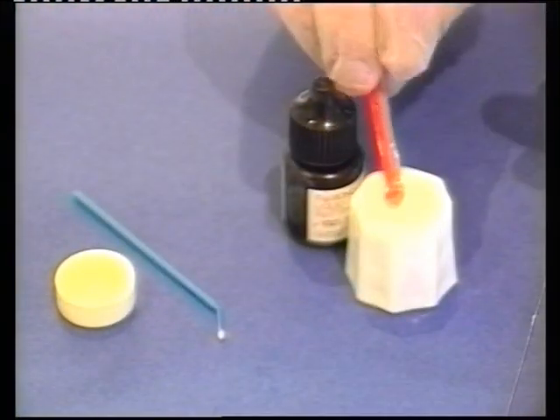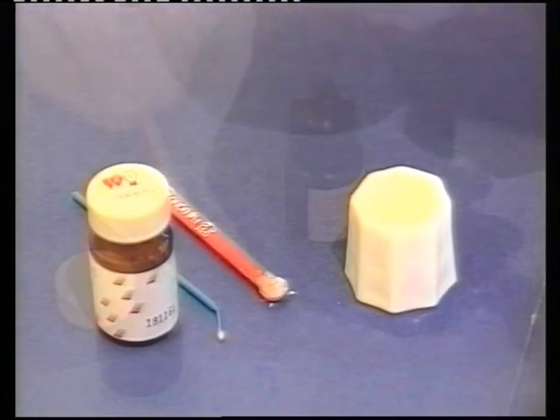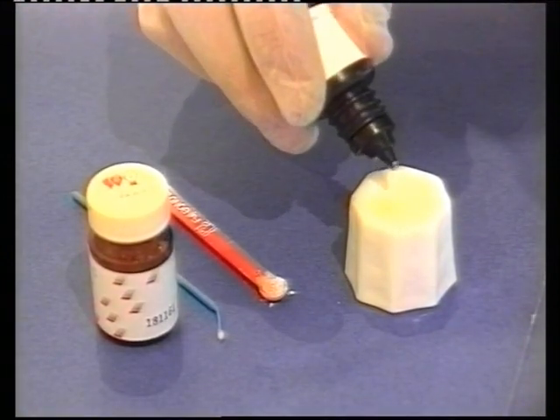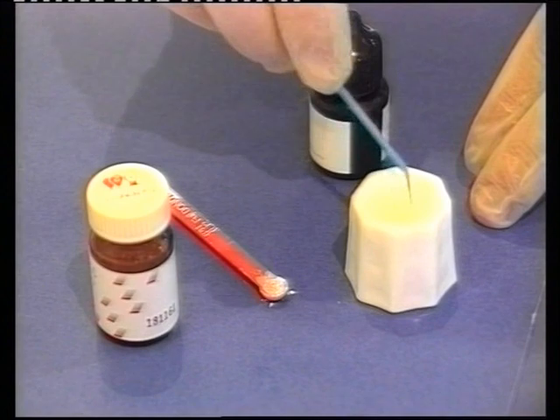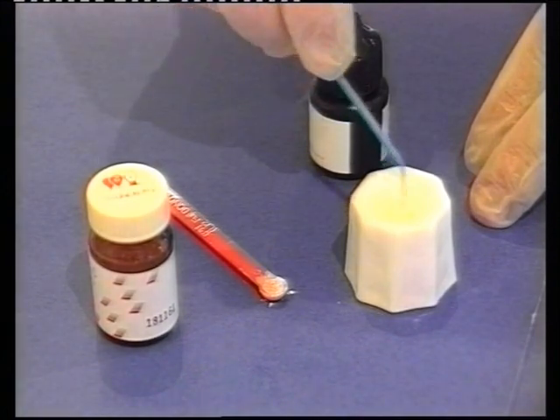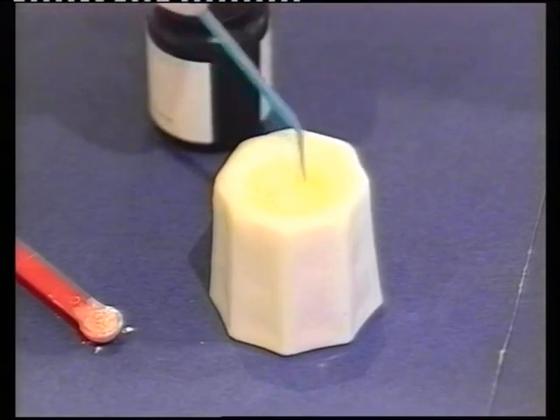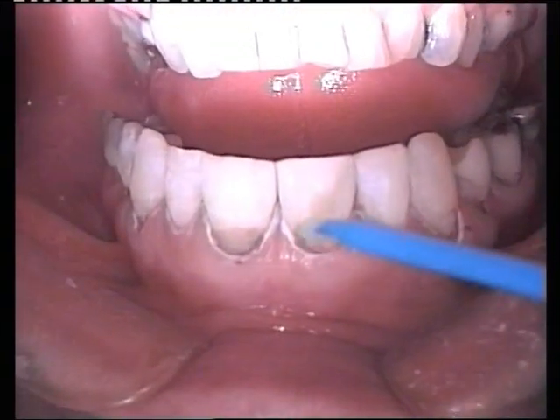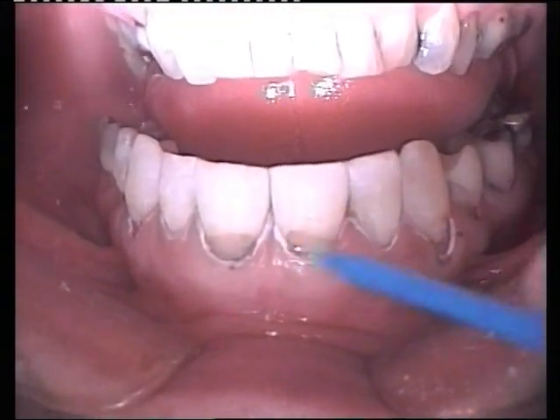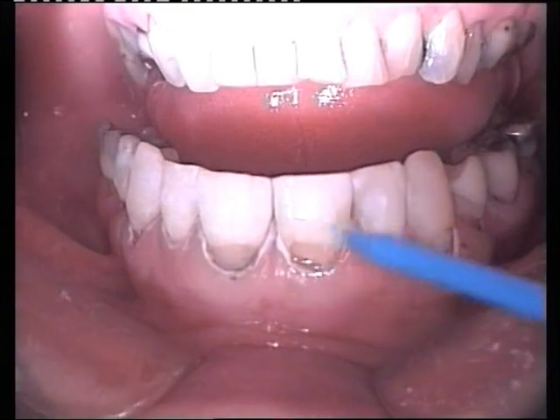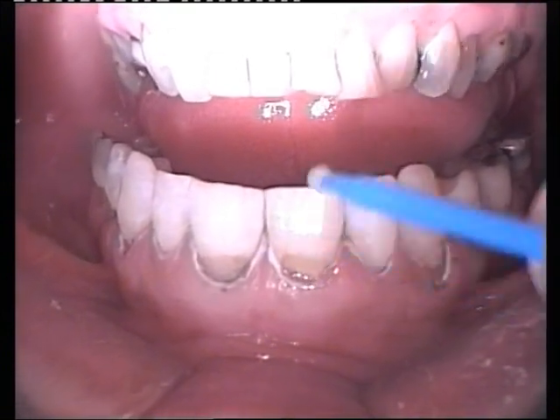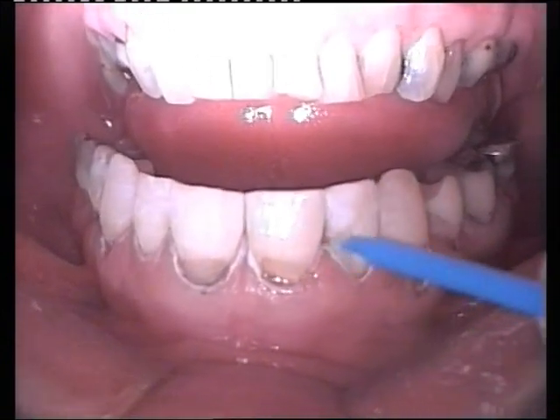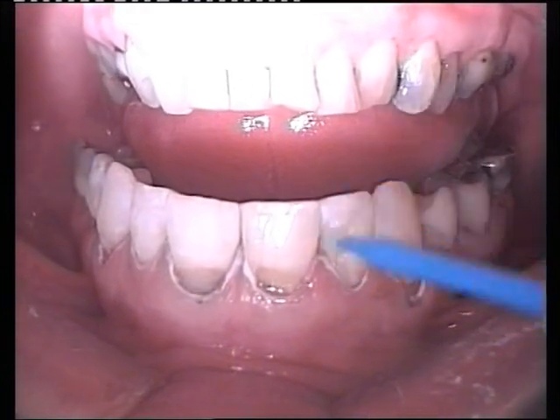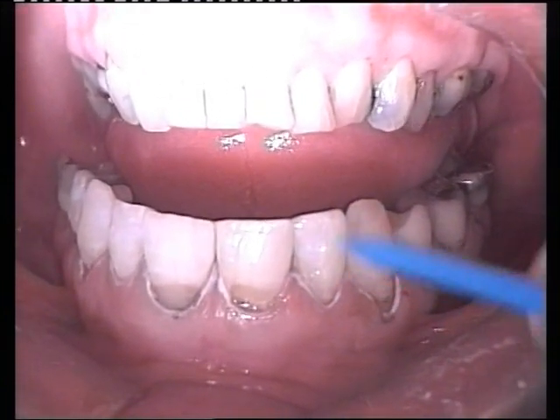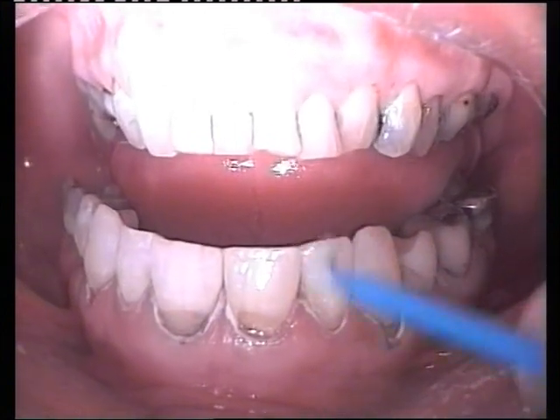A light-activated, resin-modified glass ionomer bonding agent is prepared by placing a scoop of powder and a drop of liquid in a Dappen dish and mixing with a micro brush to a creamy consistency. The resin ionomer bond is brushed over the tooth surface and cured prior to the placement of the composite resin laminates. This creates a high-quality seal and acts as a stress breaker between the brittle enamel and composite surfaces, which both have different coefficients of thermal expansion and a different modulus of elasticity.